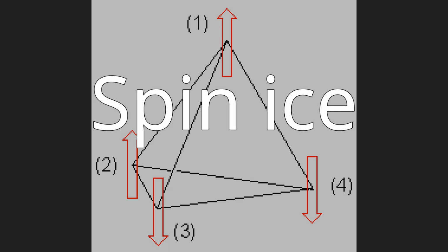This suggests a picture of Ising spins residing on the corner-sharing tetrahedral lattice with spins fixed along the local quantization axis, the cubic axis, which coincide with the lines connecting each tetrahedral vertex to the center. Every tetrahedral cell must have 2 spins pointing in and 2 pointing out in order to minimize the energy. Currently, the spin ice model has been approximately realized by real materials, most notably the rare earth pyrochlores Ho2Ti2O7, Dy2Ti2O7 and Ho2Sn2O7. These materials all show non-zero residual entropy at low temperature.